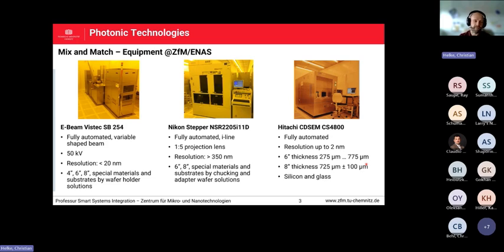For example, here the wafer needs just a minute. And for the E-beam, it can take up to 15 hours per full wafer if it's completely exposed with the E-beam itself. And on the right side, we are really lucky that we have had, I guess for 2 years, our fully automatic CDSEM from Hitachi, where we can characterize and map a complete batch of 6 and 8-inch wafers with a resolution of 2 nanometers. So full wafer characterization of our lithography and also of the process transfer into the material afterwards can be done here for every wafer, with a lot of wafers in a certain amount of time. Really, really helpful for the qualification of our own processes and possibilities here.